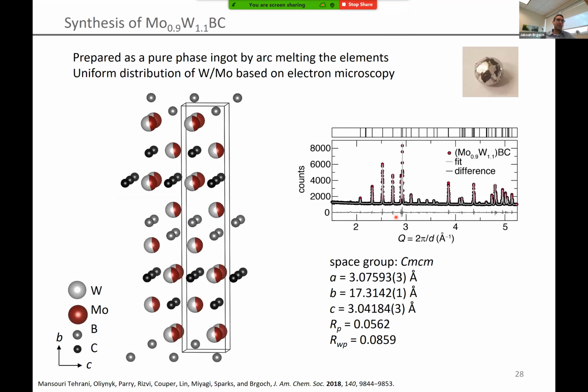So you can make molybdenum tungsten borocarbide by starting from just the elemental powders. You take the powders and mix them together so they're nice and homogeneous, press them into a pellet. We then use arc melting to melt these elements.